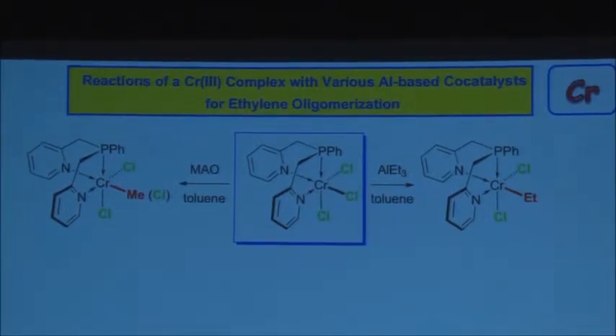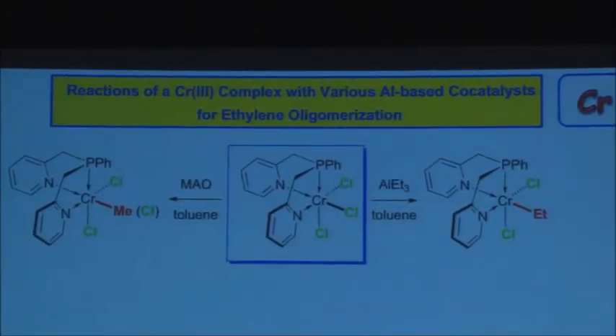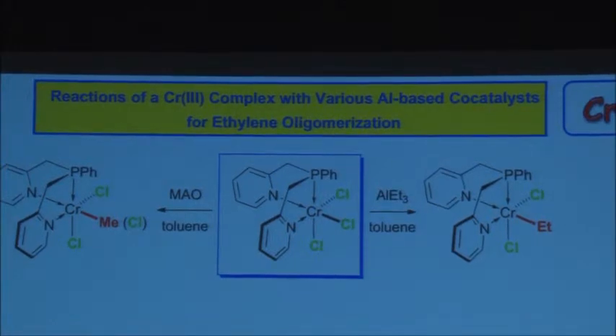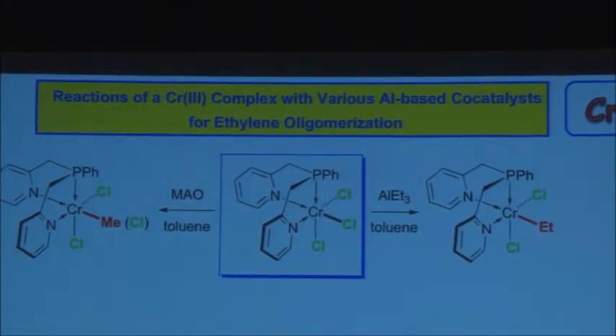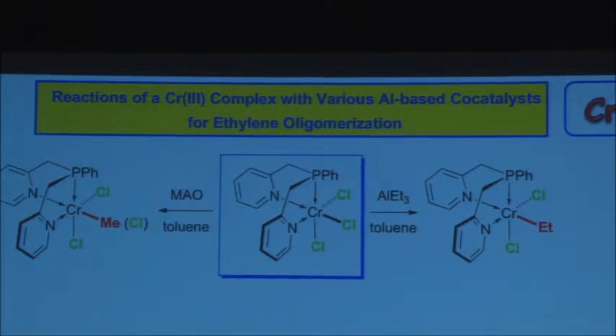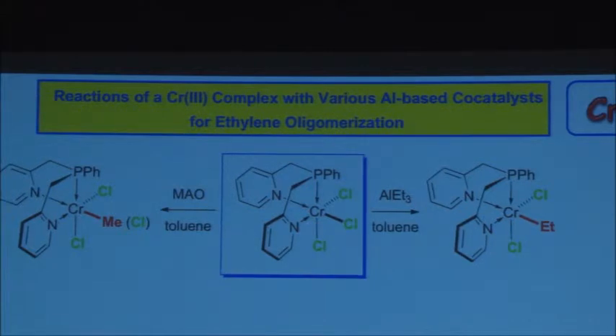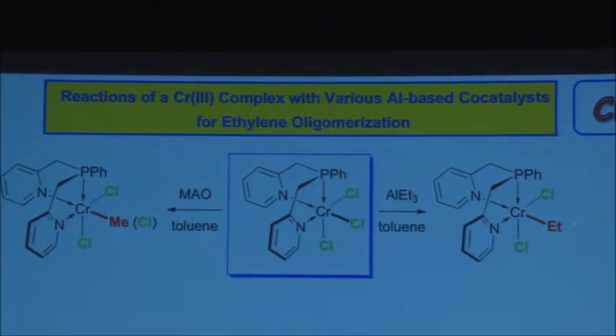And we reacted this compound in the presence of various co-catalysts for ethylene oligomerization. It is a rather active catalyst. But then I said, it'd be interesting to see whether we can isolate anything from the reaction of the pre-catalyst with the co-catalyst. We took triethyl aluminum, and what you can isolate is the alkylated compound. Ethyl group coming from the aluminum has replaced 1 chloride, but only 1 chloride has been substituted. I'm not saying that this transformation is quantitative, but this is the compound we could isolate and characterize fully.